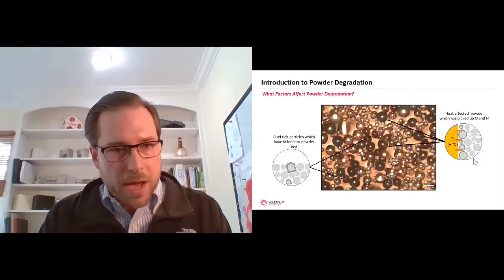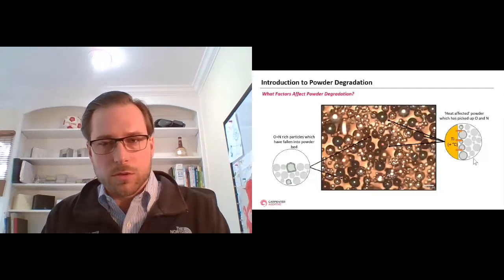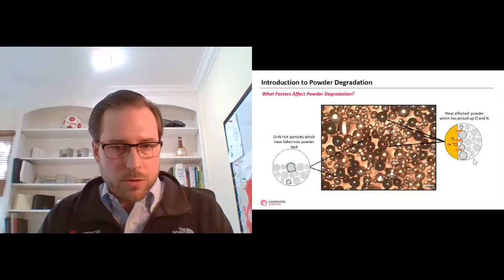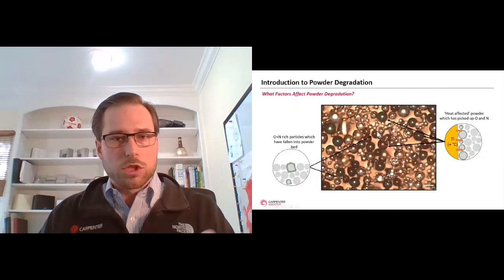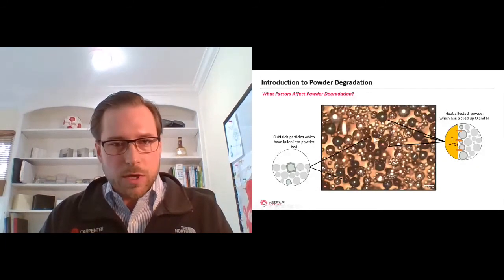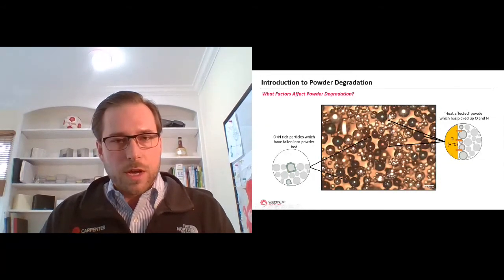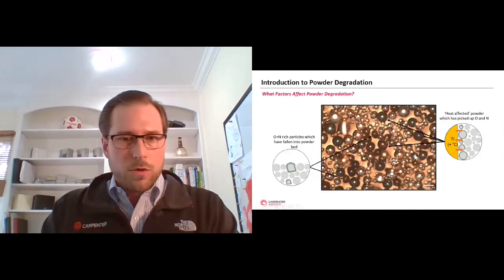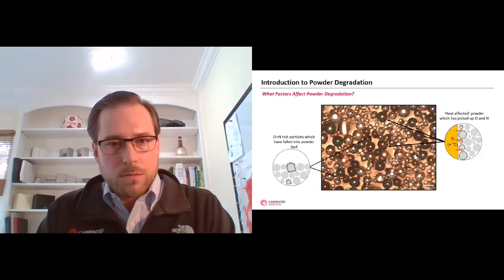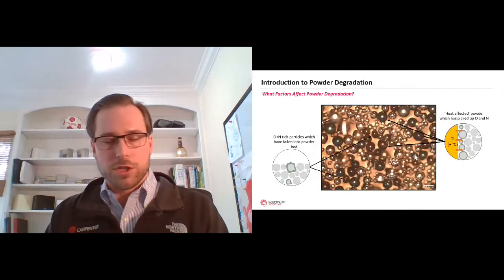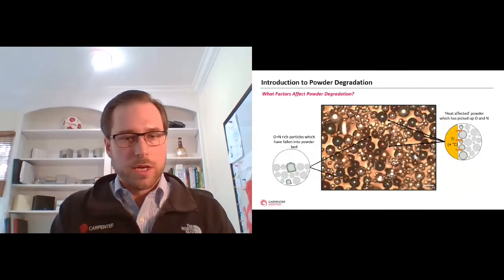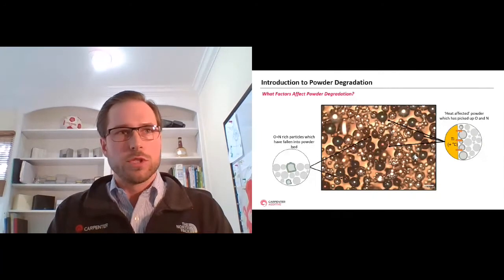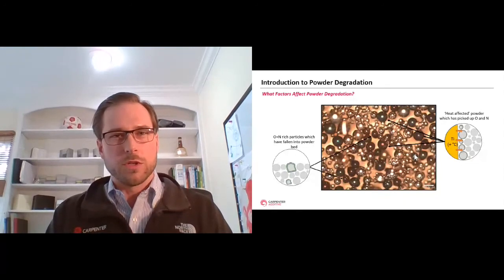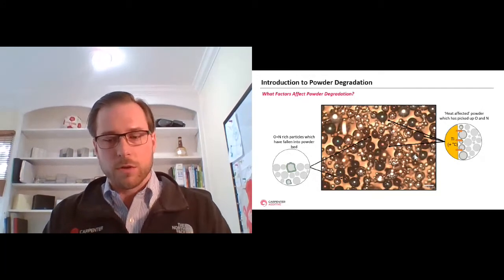Okay, so when we look at the powder, you can see some of these particles that are impacted. So we see misshapen particles, which are still small enough that they make it through the recycling process, but they've significantly oxidized, and we see these heat affected zone particles that are still very spherical but have oxidized. So it's really important to be able to identify how much degradation you're seeing by taking real measurements, not by characterizing as once used, twice used, three uses. We use that terminology a lot because it's a simple way that people can understand it. But the reality of it is that every application and every production scenario will have different degradation rates.